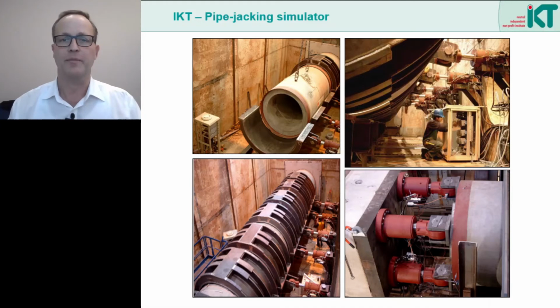In these pictures, we see how the test stand looks like in reality. In the upper left corner, the pipes are placed in the steel frames. Under the pipes and on their sides, hydraulic cushions are positioned as bedding. Below we see how the pipes are placed one behind the other and how they can be positioned with the horizontal pressure jacks. On the top right, we see our measurement technician working directly under the horizontal jacks. And below on the right, there you can see the main jacking cylinders. With these, we were able to apply jacking forces of 8 meganewton, which is about 800 tons. This is quite representative of a typical pipe jacking site and well enough for our sample route.